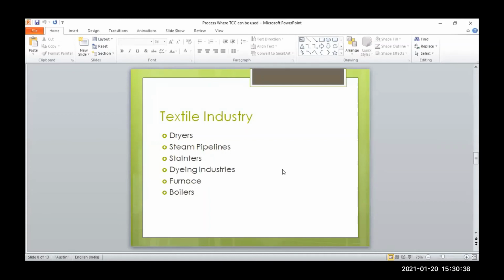Here in dryers, where the cloth is dried on dry rollers, both ends of the dryers can be applied with this coating. We had one very specific requirement from one of the textile industries where we used that coating. There was a drop of at least 20% in temperature on the external shell of that dryer.